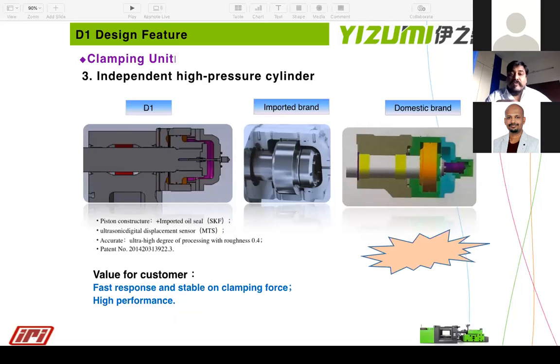Okay, and we also have another patent, independent high pressure cylinders. All 4 cylinders in the two platen machine are independent cylinders monitored by an ultrasonic stroke transducer, and this is our patent. So what is the advantage here? The clamping force build up is very fast, within 0.3 or 0.4 seconds.